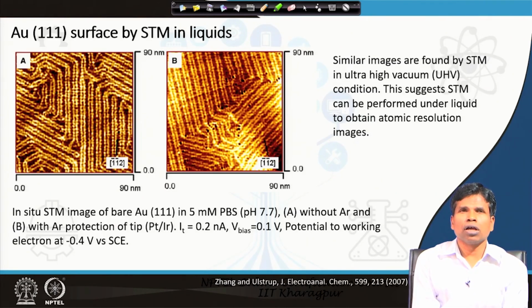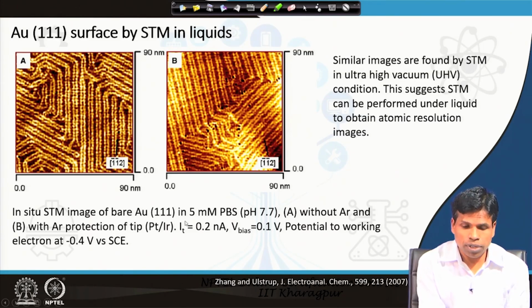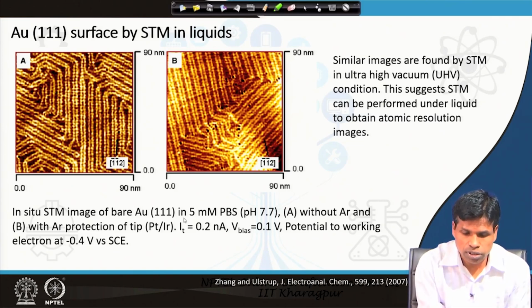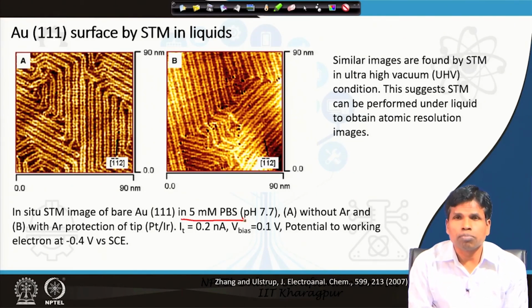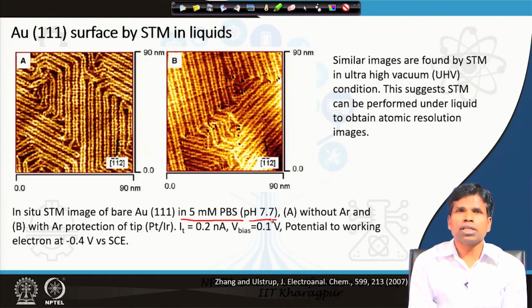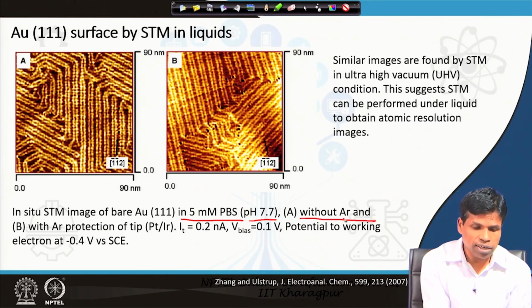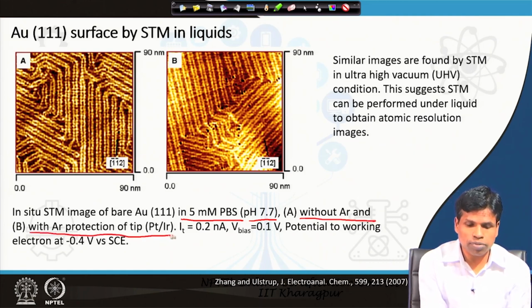This is an example of a gold sample. This gold 1-1-1 surface image was collected under liquid, and in this case the liquid was 5 millimolar phosphate buffer solution at a pH of 7.7. This image was collected in two conditions. One was without argon, and another was with argon protection of the tip.